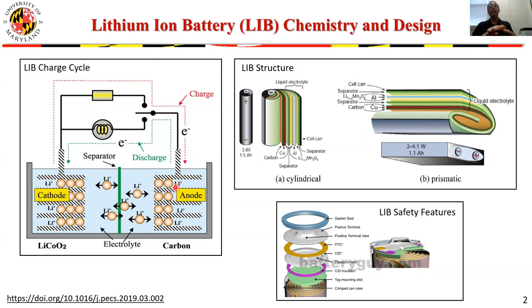So when you give an opportunity for the electron to travel, lithium atoms ditch their electron, move through the electrolyte, which is typically an organic carbonate, and get incorporated back into the cathode. Practically, this system is realized in various structures, such as shown on the top right side of the slide. Typically, in an actual lithium-ion cell, the cathode and anode materials are coated onto the current carriers, which are usually copper and aluminum foils.